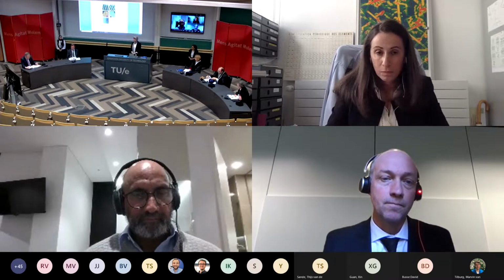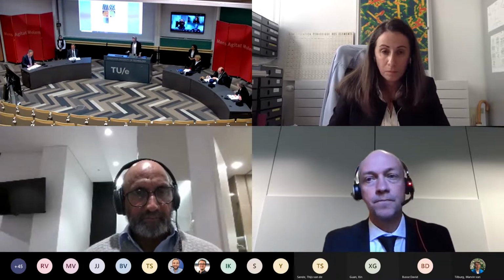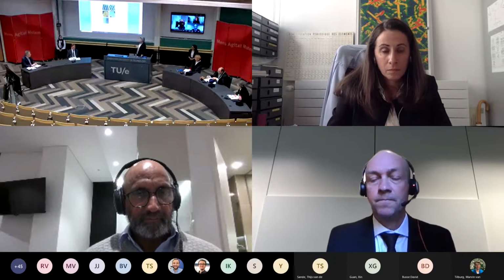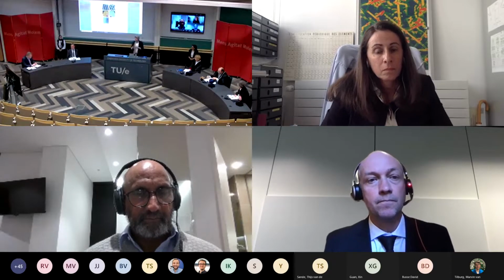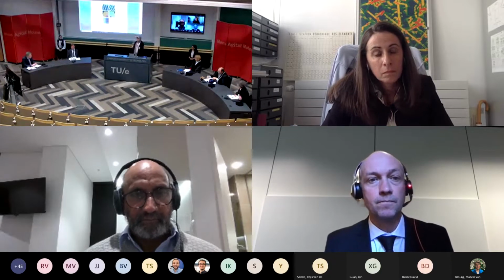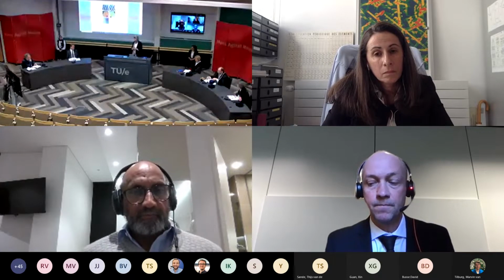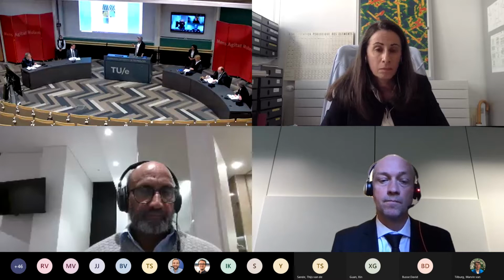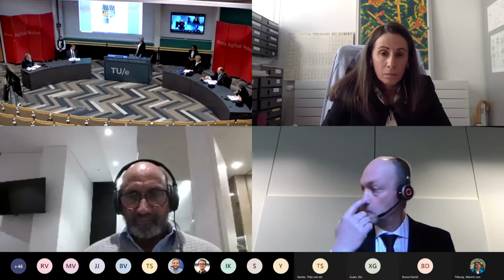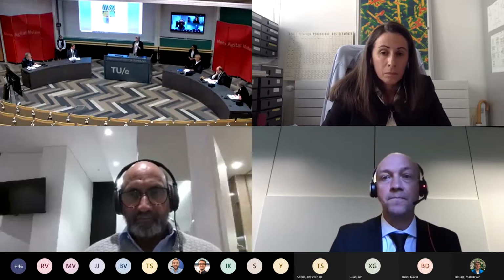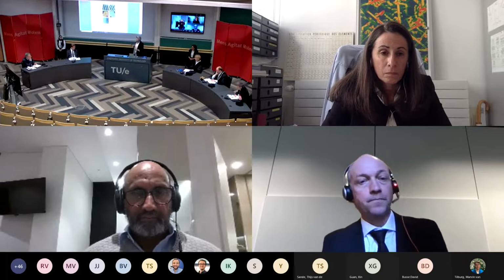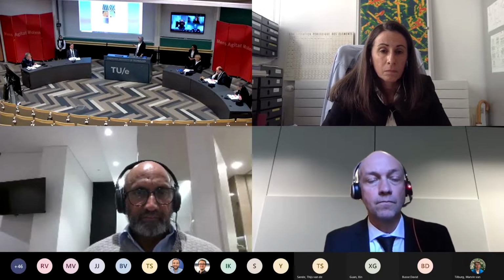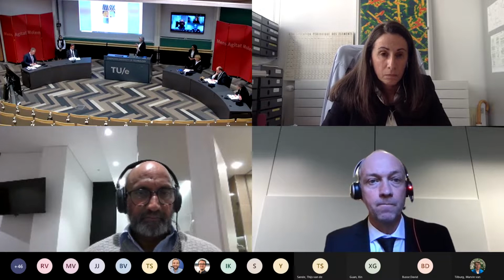The opponent, thank you so much for the questions. I will start with the first question about the EDX. The EDX we have performed here, we performed in a transmission electron microscope. So we shoot our sample with high energy electrons, and then we look at the characteristic X-rays emitted from our sample. Based on the characteristic X-rays from every element, we can map the elements in our structure. So we can see here a compositional map of the different elements that exist in our structure.